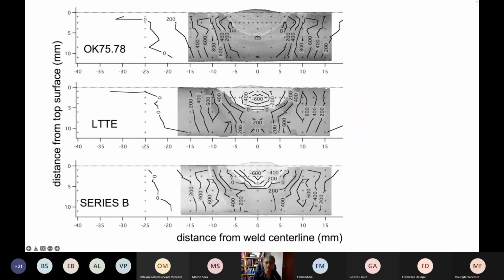This is our control electrode, and you can see that we've got large tensile stresses here in the heat affected zone and so forth. These two are the low temperature transforming welding alloys. And look, we've got minus 600 megapascals of compressive stress here, and similarly minus 600 here. Okay, so this method actually works, and there are many tests now in the literature, going from the work of Ota and so forth, which show that actually the fatigue properties are improved because of this compressive stress system that you develop.